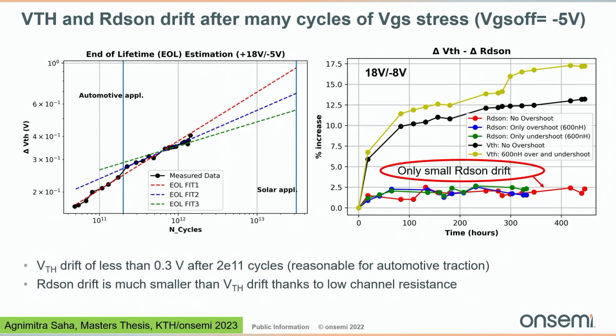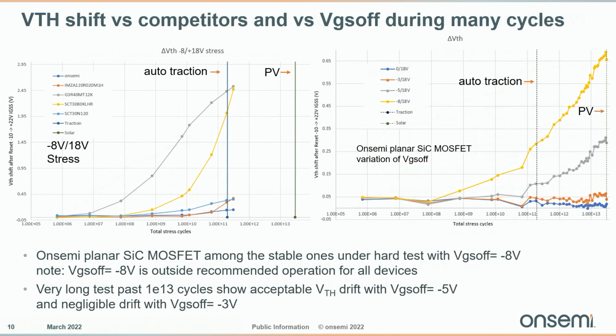And then, measuring many cycles here, you can see that the 2E11 cycles, which is often quoted to be around a typical automotive mission profile for automotive drivetrain, we have less than 0.3 volt shift, so it's not so bad. And the RDS-on drift, you can see to the right, is really small, thanks to the low channel resistance. And the right graph was measured with -8 volt Vgs off. So that's even more accelerated.